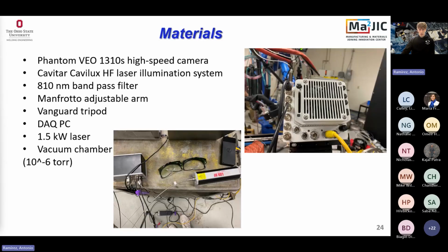So for materials, we used the Phantom VEO 1310s high-speed camera. We have our laser illumination system here, and some other smaller setup things. Our vacuum chamber goes down to 10 to the -6 torr, which is very, very low pressure. That is considered high vacuum. And then a 1.5 kilowatt max output laser.